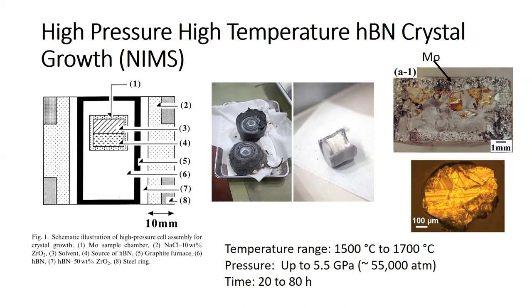But in their process, they seal the boron nitride source and the solvent, which is barium boron nitride, into this molybdenum crucible. Then they put a pressure of 55,000 atmospheres on it and heat it up to this temperature. And they grow the best quality material, without a doubt. And they have shared it with lots of people. But